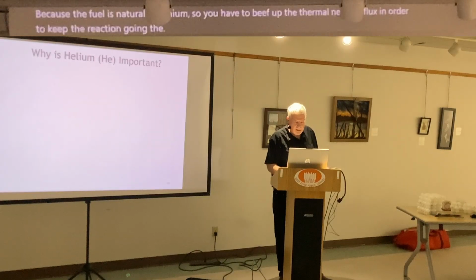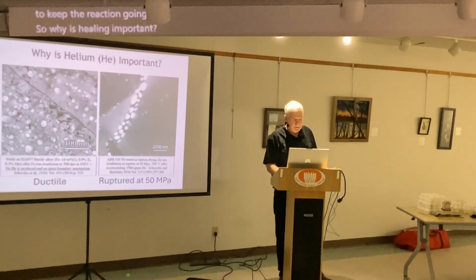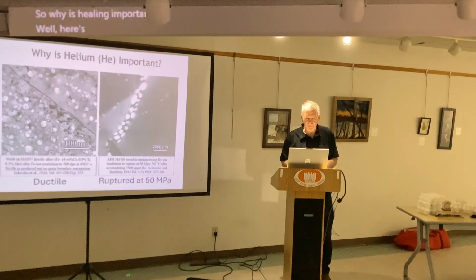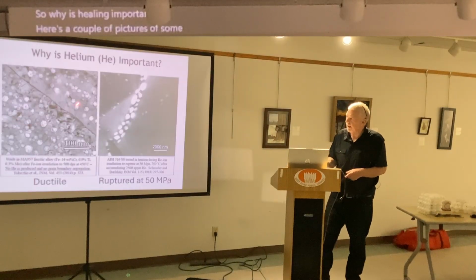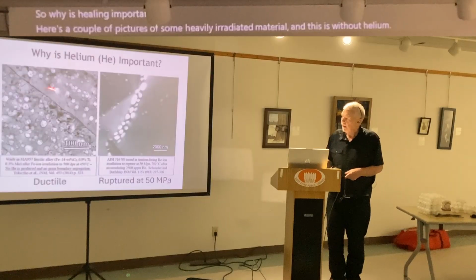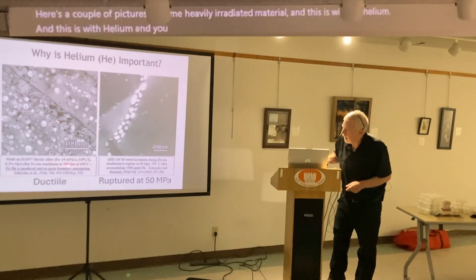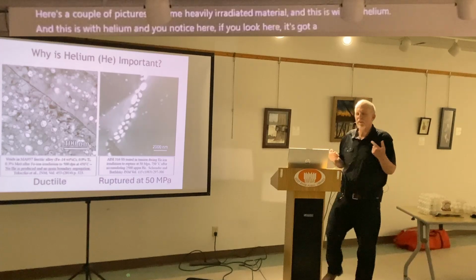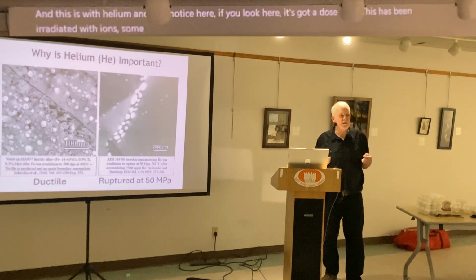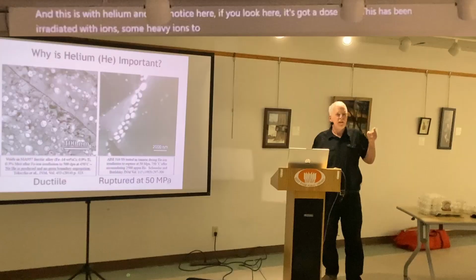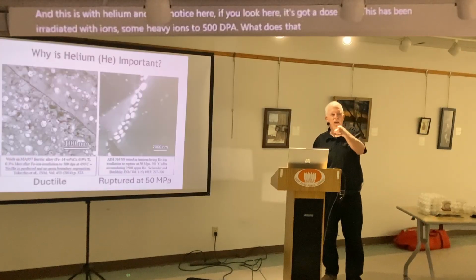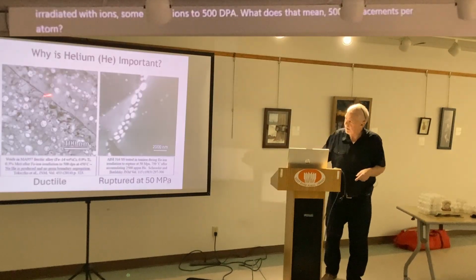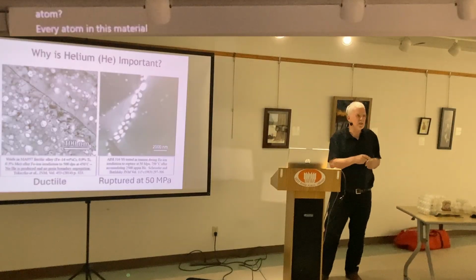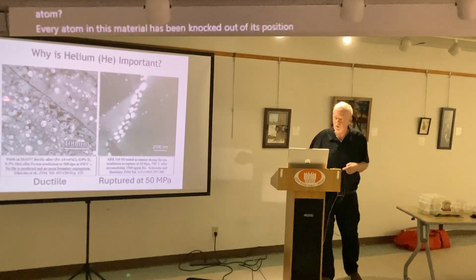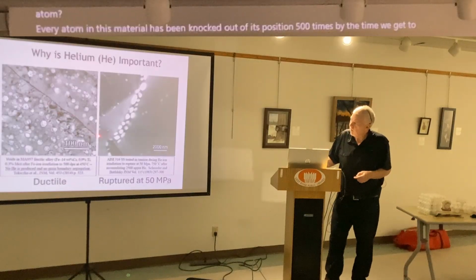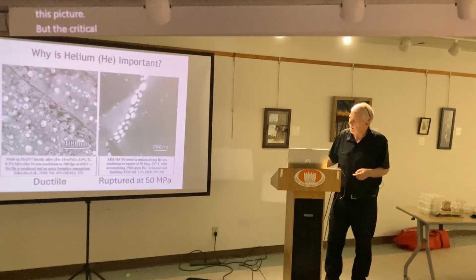So why is helium important? Well, here's a couple of pictures of some heavily irradiated material, and this is without helium, and this is with helium. And you notice here, it's got a dose. This has been irradiated with heavy ions to 500 dpa. What does that mean? 500 displacements per atom. Every atom in this material has been knocked out of its position 500 times by the time we get to this picture. But the critical bit is the boundary. It's nice and clean.